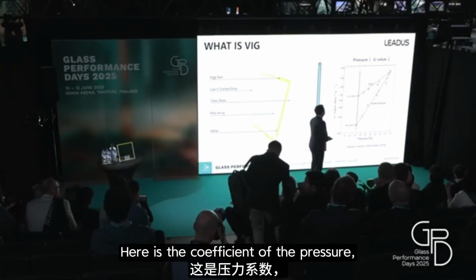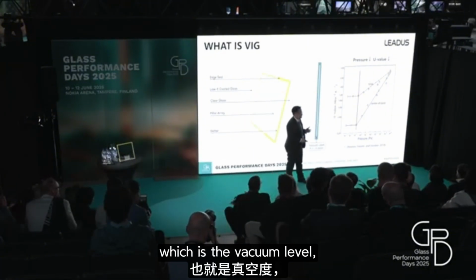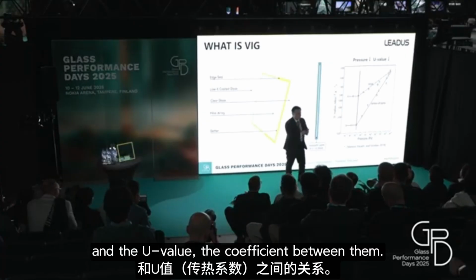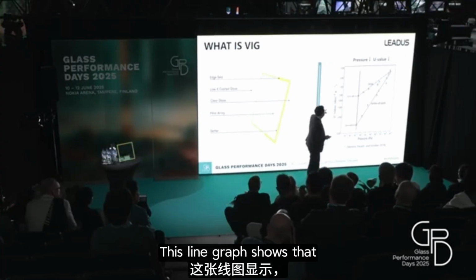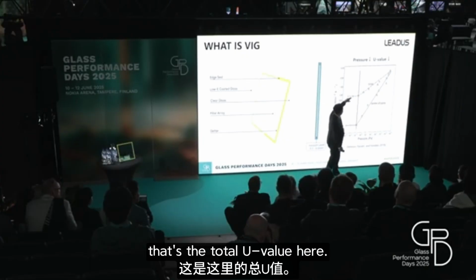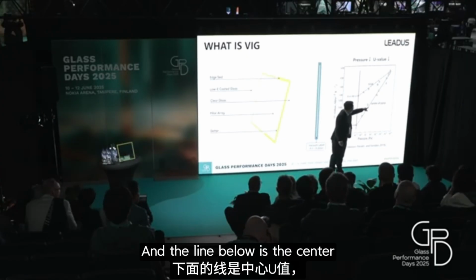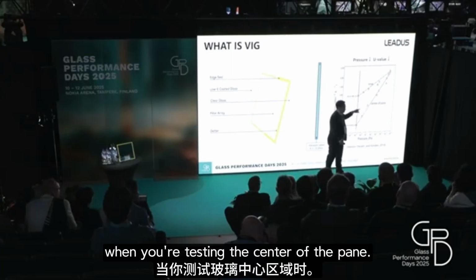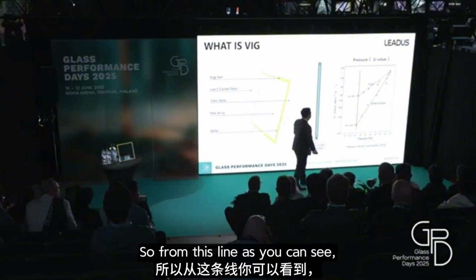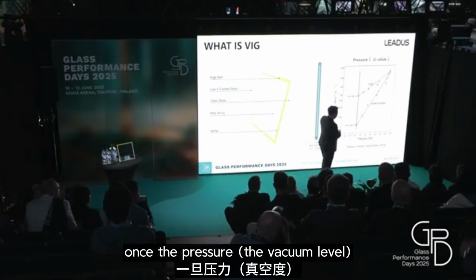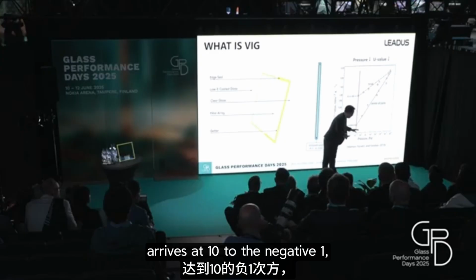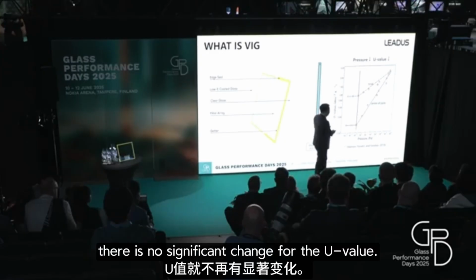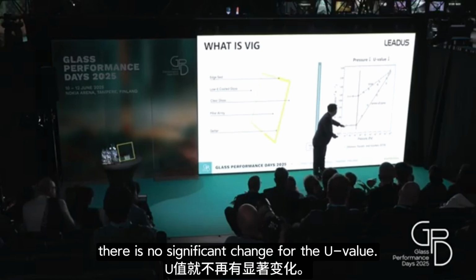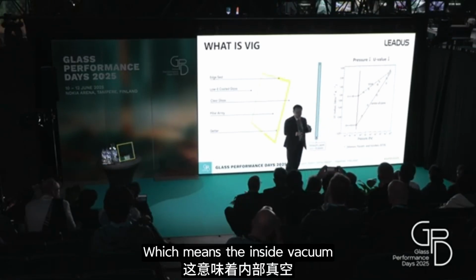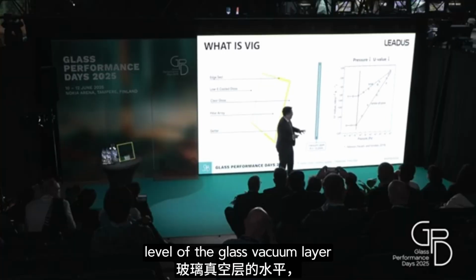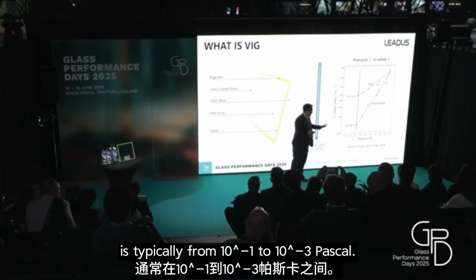Here is the relationship between pressure, which is the vacuum level, and the U value. This line graph shows that this line over there is the total U value, and the line below is the center-of-pane value when you're testing the center of the pane. From this graph, you can see that once the pressure, the vacuum level, arrives at 10^-1, there is no significant change for the U value. This means the inside vacuum level of the glass vacuum layer is from 10^-1 to 10^-3 Pascal.